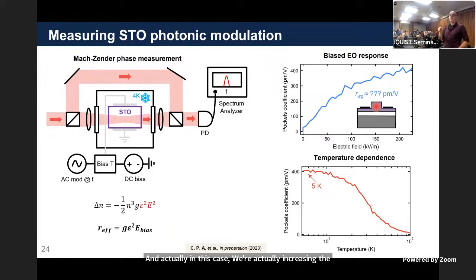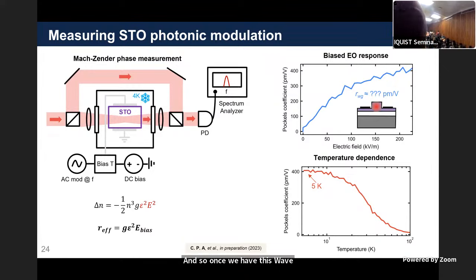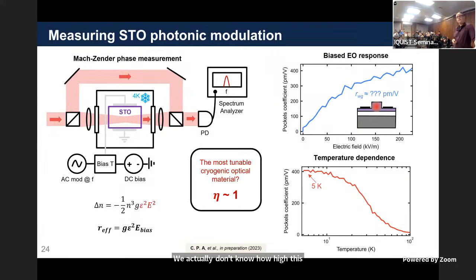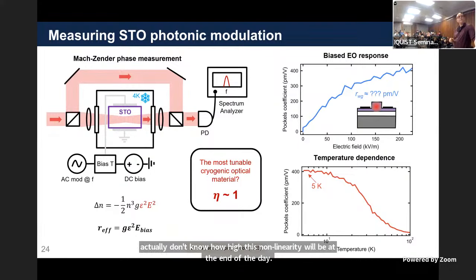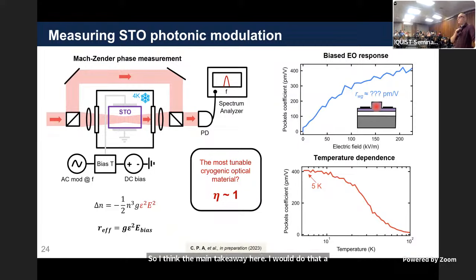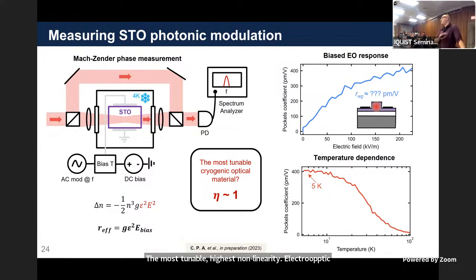And because this is a large crystal, we have a 200 volt source. It's a 1 millimeter crystal. That's the end of this plot, and it was still going up. So once we have a waveguide with around 5-10 microns of gap, we actually don't know how high this nonlinearity will be at the end of the day. The main takeaway here, I went through that a little fast, is we've already discovered the most tunable, highest nonlinearity electro-optic crystal at low temperatures. And that's exactly what you want for doing quantum photonic tasks at low temperature.